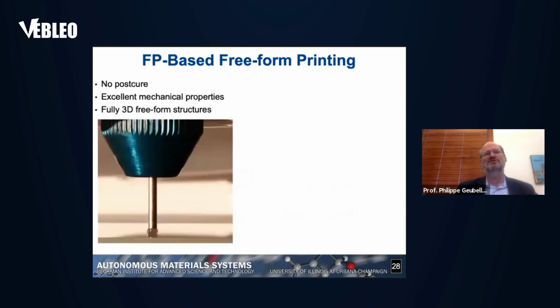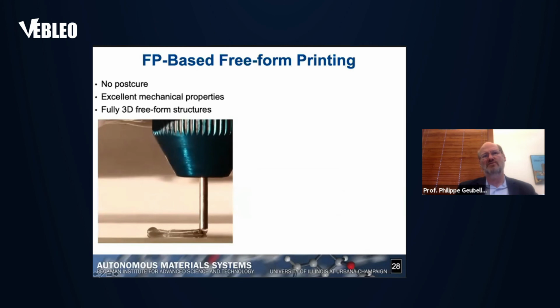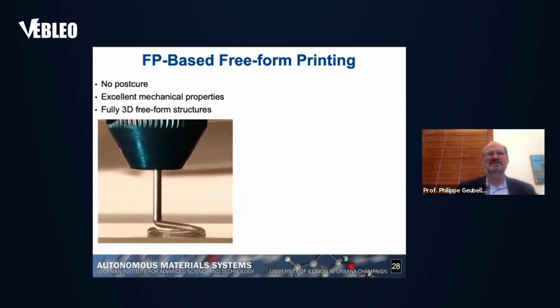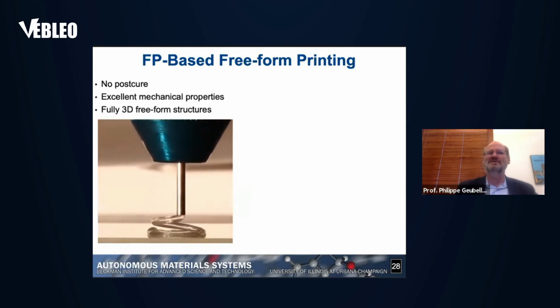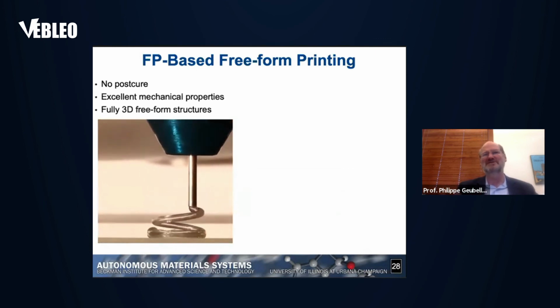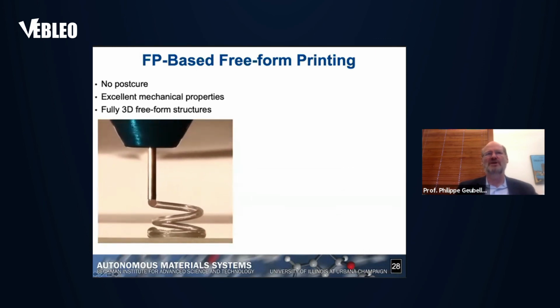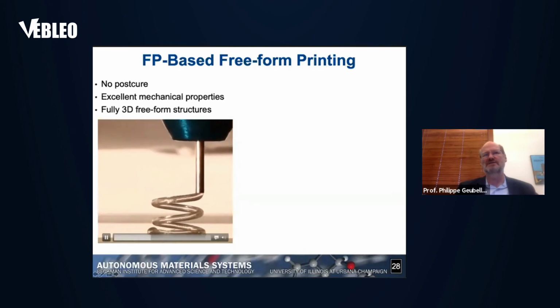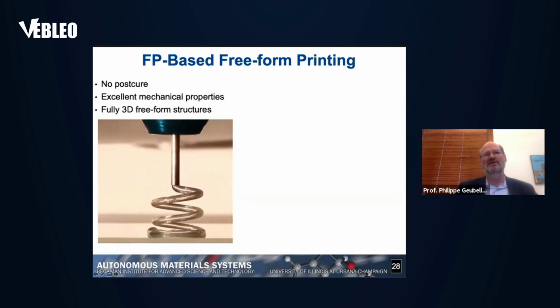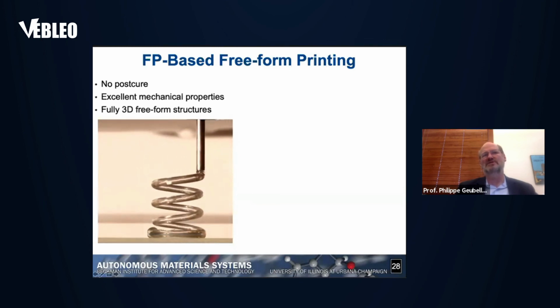And so that allows us to achieve these kind of situation where we can make, in this case, a relatively simple part, but it's a fully free-form, self-standing type of structure. You can see here that as soon as you deposit the gel, the front tends to follow the printing process and polymerize the material right on the spot. And that really allows us to achieve really unique forms, right? Free forms without the need of scaffolding or anything like this, and still achieve excellent mechanical properties.